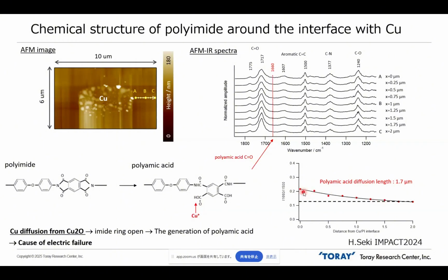So this graph shows the copper diffusion length. The copper diffusion length in this case is around 1.7 micrometers. In this sample, the copper interconnect pitch is on the order of 5 micrometers. So in this case, the diffusion length is not such a big problem, but as the pitch of the copper interconnect becomes narrower, smaller, this diffusion length may cause problems regarding electric failure.